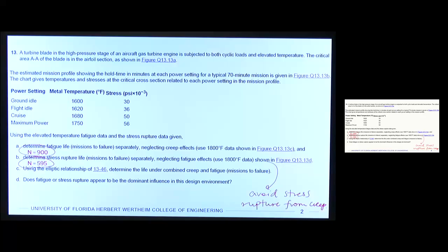We talked a little bit about how to combine those two effects. What we did was take the Goodman equation, which is usually used for handling fatigue when you have non-zero mean stresses, and instead of the ultimate strength, we substituted in a strain-limited critical stress, sigma CR.